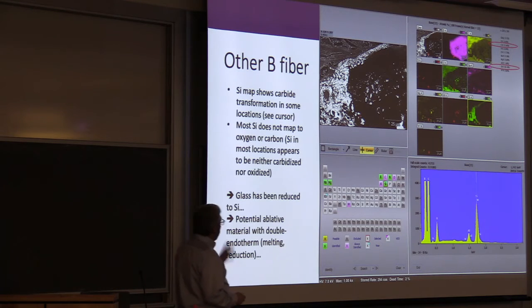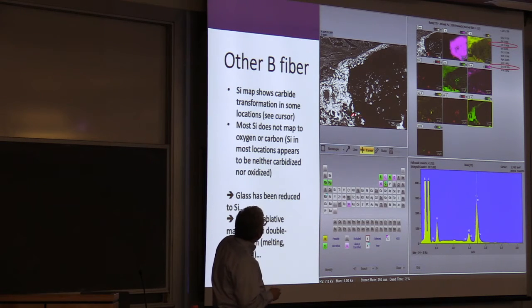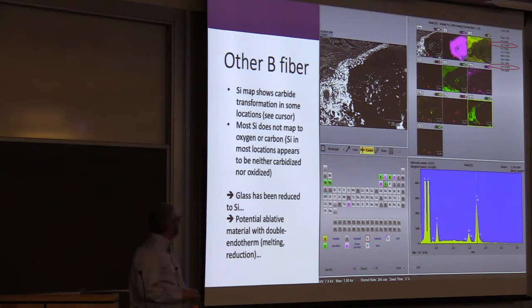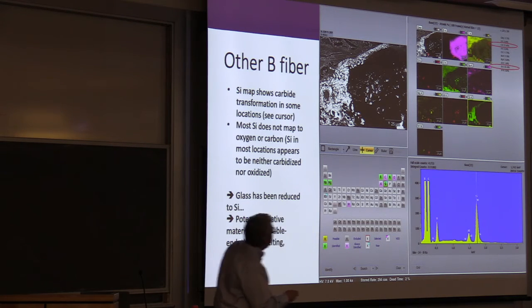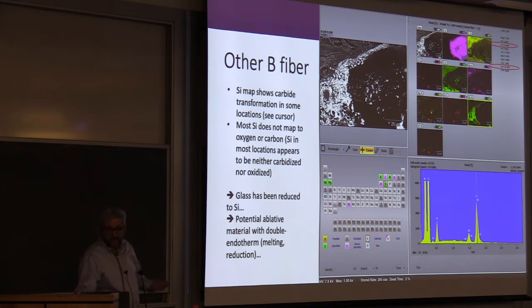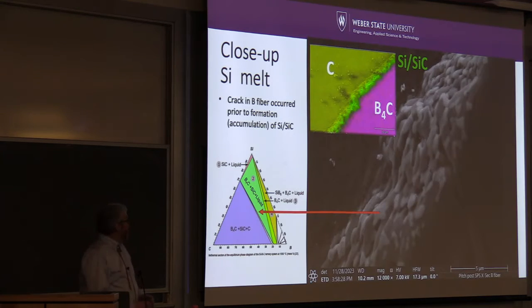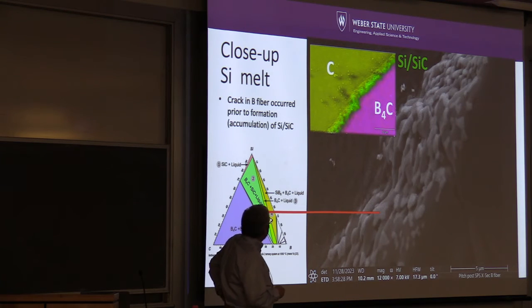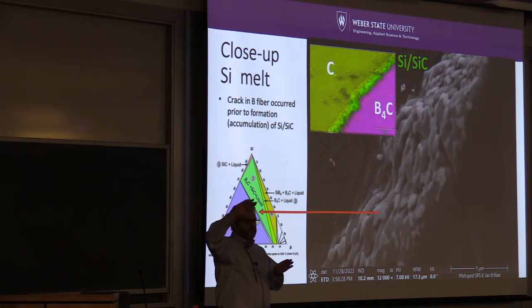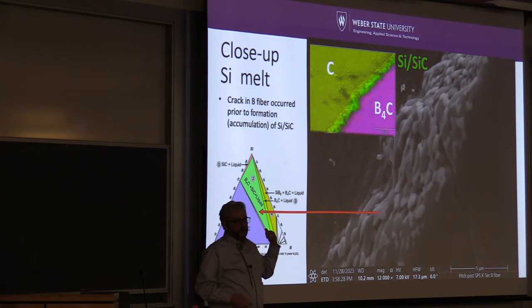I looked at another one of those fiber cross sections, and I'm like, what is that? Aside from the boron carbide that you see, which I thought was fascinating, to have converted that boron fiber to boron carbide, that was pretty cool. But what is going on there on the edge? And I get this rich carbon, I get this boron carbide over here, and then on this edge, and again, it's a raised edge, even though I polished it, this thing is really hard right here.